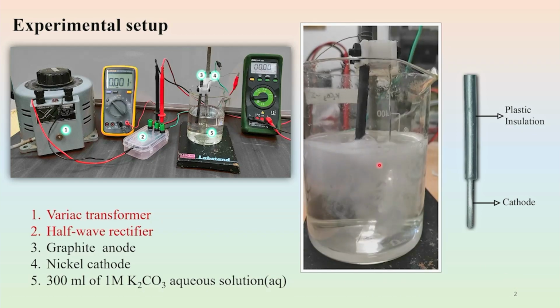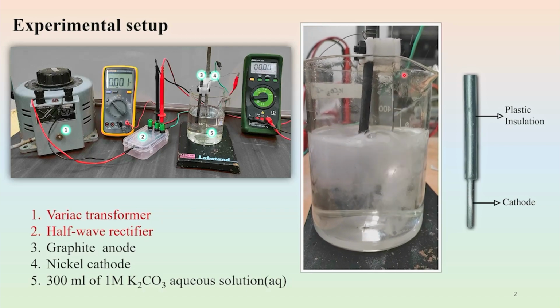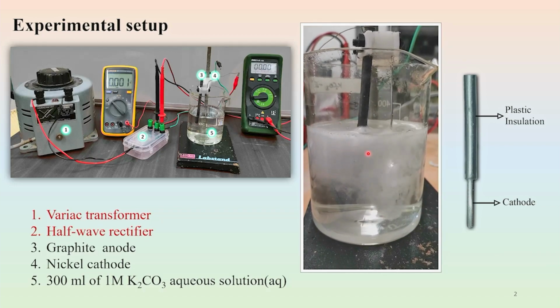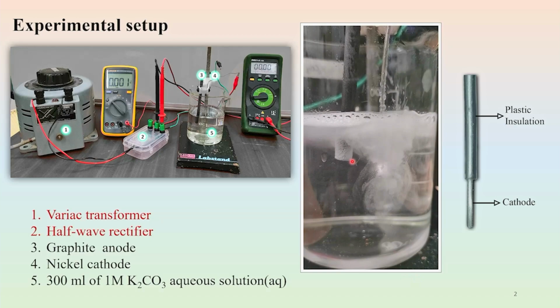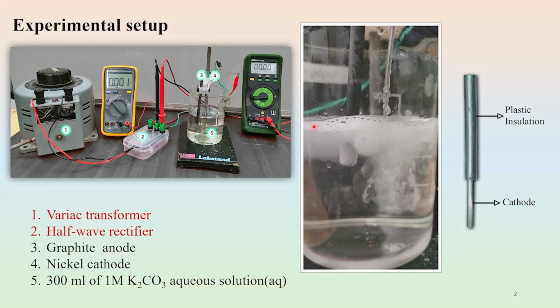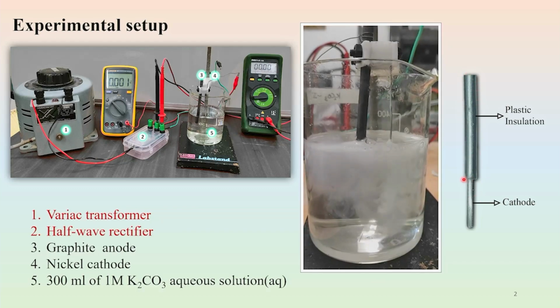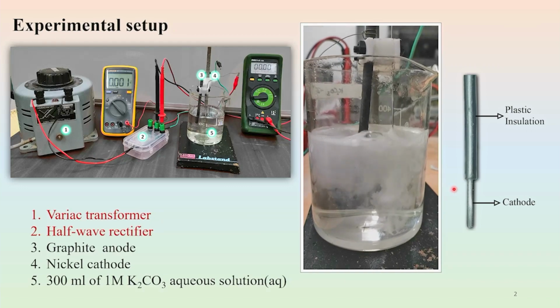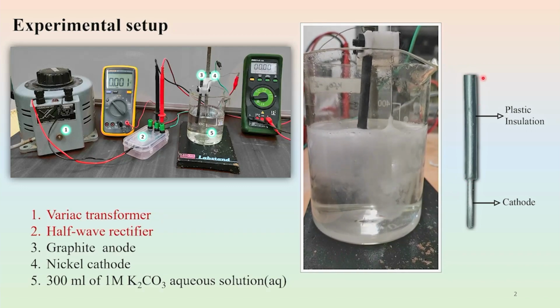So this is clear, how insulation makes a difference. Without the insulation, the reaction is very violent and the solution keeps spilling out of the beaker. To prevent the spilling, insulation is used, and it gives us the freedom to dip the cathode deeper inside the solution. And the effective reaction area can be controlled by adjusting the height of the insulation. Here, the insulation is a hydrocarbon polymer.